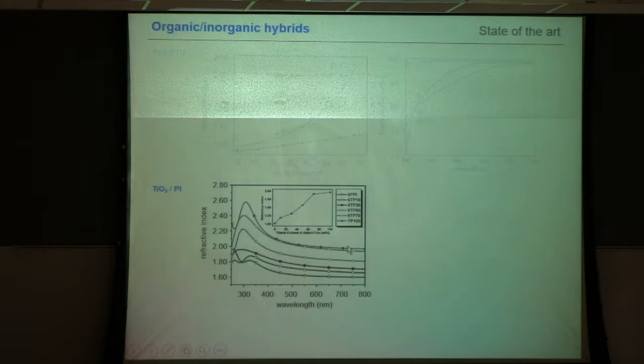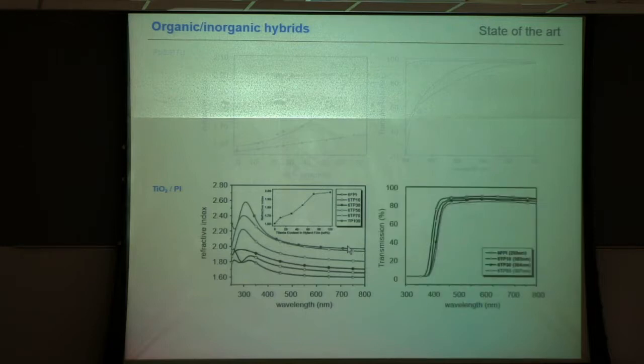In reality, I believe there's more like an inorganic polymer made up of titanium, oxygen, and titanium. And when they actually measured the refractive index, they saw also pretty much an increase of refractive index. And in this case, they actually got what is pretty desirable. So the polymer is essentially unaffected by the particles, and the hybrid and the neat polymer